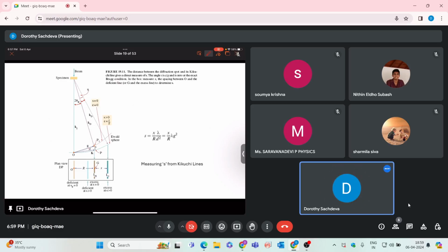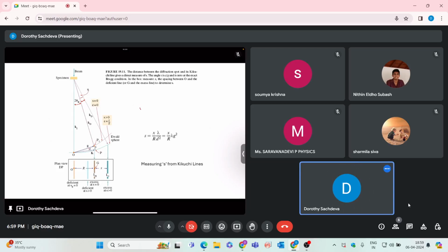Then we'll discuss this factor S. So basically, you have your deviation parameter S. We already discussed that when your specimen is in the nanometer regime, you have railroads in the reciprocal space. So basically, the spots which you are seeing in the diffraction pattern are not one single spot, rather it is an elongated rod in the perpendicular direction in which it is in the nanometer range.